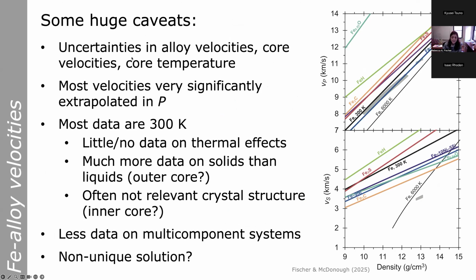There's uncertainties in the velocities of these alloys, in the velocity of the core, in the temperature of the core. Even more so than with the equations of state, most of these velocities are very significantly extrapolated in pressure to make this figure, kind of recklessly, sorry to the authors of these original studies. And most of the data that we have are at 300 K. Again, certainly not all of it, but much of the high temperature data we do have is at relatively modest temperatures relative to the core. So for some of these materials, we really don't know all that much about the thermal effects on their velocities.